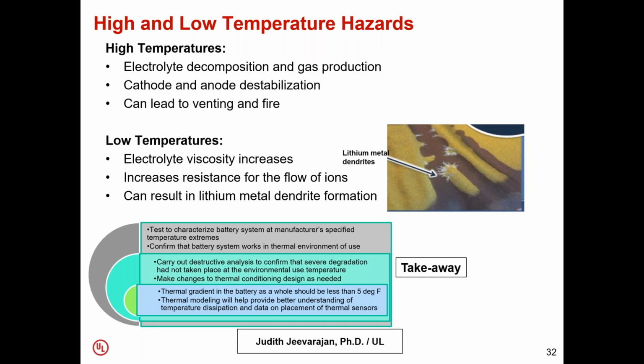And carry out some destructive testing to see if any severe degradation has taken place. And if there is, then you can make changes to the thermal conditioning that is happening to the cells and the battery, so you can improve the design. Thermal modeling also helps quite a bit with understanding where you need to put your thermal sensors and what the heat dissipation paths of your battery are. I would usually recommend a really small thermal gradient within the entire battery. I recommend 5 degrees F, which is really difficult to get, but that has been something that we have imposed on some of our applications in my previous career.